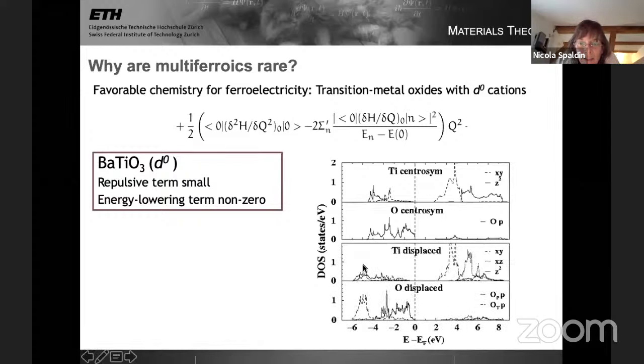You see this in the density of states in the lower panels here. When I displace the titanium, see how the density of states changes from the centrosymmetric case. The bottom of the band is shifting down in energy and hybridizing strongly with the oxygen. So this is yet another way of seeing the kind of cartoon picture I showed just before.